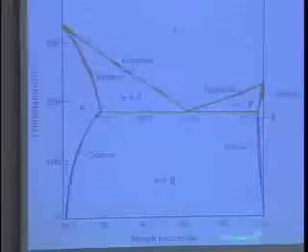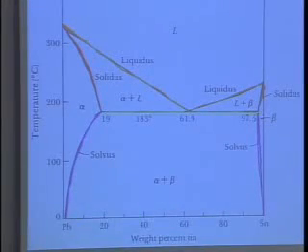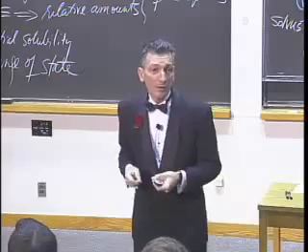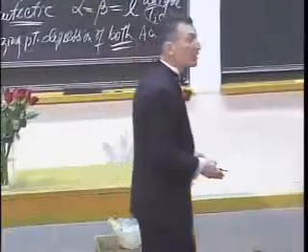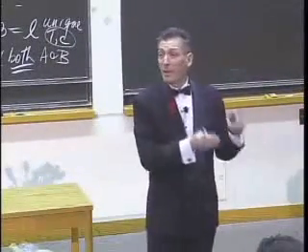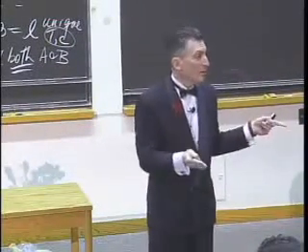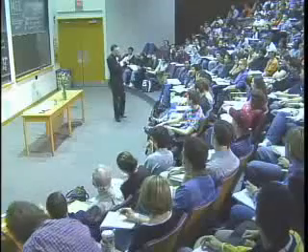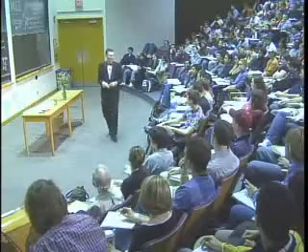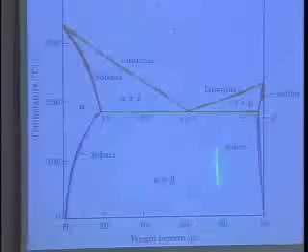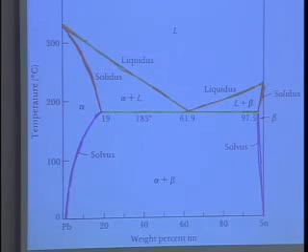So right now, there's a huge effort to look at lead-free solders. Lead, mercifully, has this low melting eutectic below 200 degrees Celsius. That's the good news. The bad news is it's lead. And so now we've got two alternatives, and that's something that you're going to be faced with. Either we have something that is lead-free and very costly, more costly than the device itself, or we have something that is not terribly effective. It cold freezes in the joint, and joints pop off, and so on. So this is a eutectic diagram indicating the value of freezing point depression in processing.